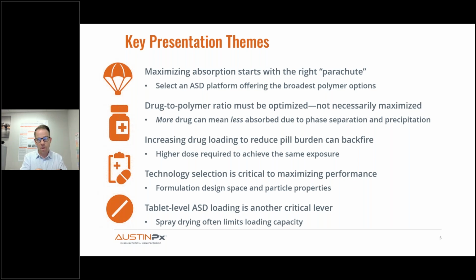And as many of you on this webinar know, spray drying often limits loading capacity of the SDD in the final tablet because you need to dilute the SDD prior to dry granulation roller compaction and then dilute once again moving into tableting. So spray drying is at a disadvantage in the amount of external excipients one has to apply to the ASD in order to achieve an acceptable tablet.